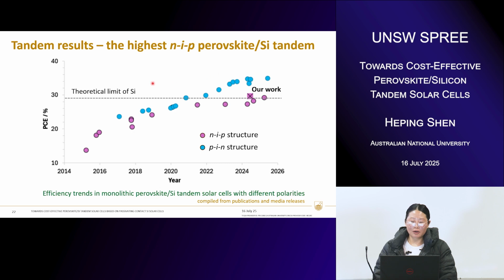So I won't discuss too much about the details. We can of course take that into discussion later in the Q&A session. But this is another important open question that needs to be answered, which is whether tandems should be on NIP or on PIN, because both structures have their own advantages, but also their own challenges. For example, PIN, which is the major technology that people have been focusing on, has the challenge of relatively high absorption loss from the carbon-60, which is usually used as the electron transporter material on top of the perovskite, but also mechanical instability from this carbon-60 and the perovskite layers.